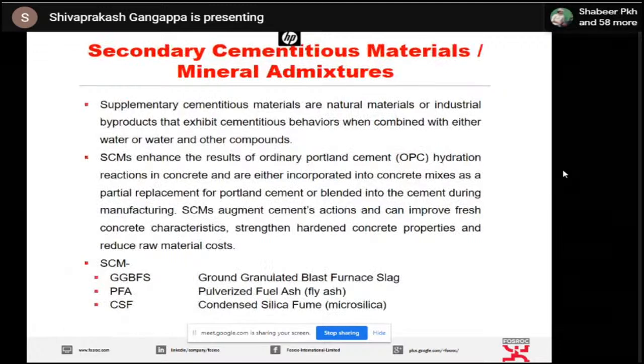Now, as I told you, we are in a position to use only the OPC cement, but OPC cement of 450 kg is not enough. Now I want to add some more binder. So what other binders can I add? There are secondary mineral admixtures in producing higher strength or high performance concrete. What is this secondary cementitious material? You all know this one is ground granulated blast furnace slag, and the second thing is fly ash. So these two are the secondary cementitious materials. We call them SCMs. SCMs basically replace OPC.